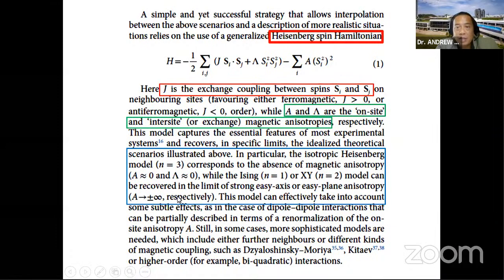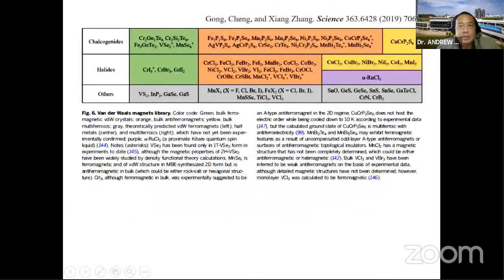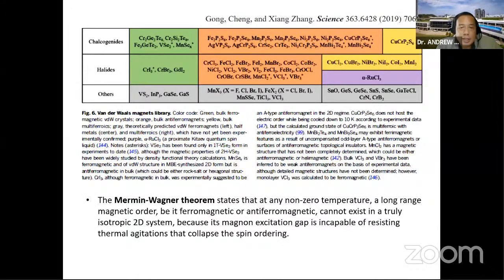A can be some finite value, and hence this explains the properties of the material. So if you can introduce some anisotropy in your material, then these terms are non-zero, and then you can get 2D magnetism, right? So this is an early review in Science where it summarizes the 2D magnets that have been discovered up to then. So here, again, the Mermin-Wagner theorem says that 2D materials that are isotropic cannot be magnetic, but you can introduce some anisotropy.